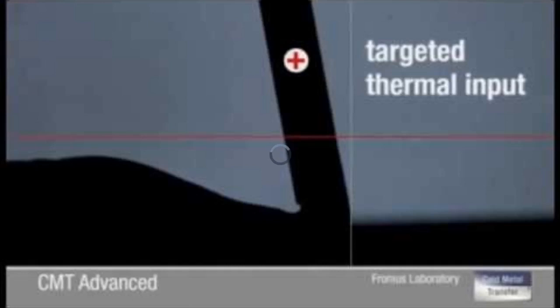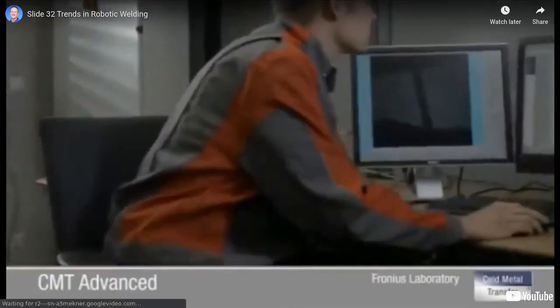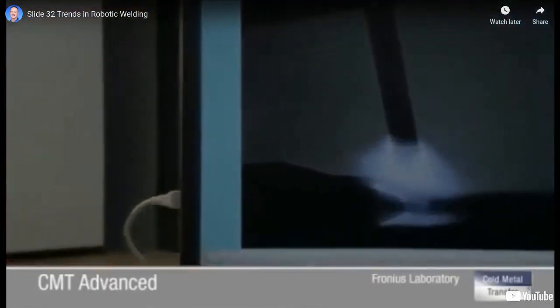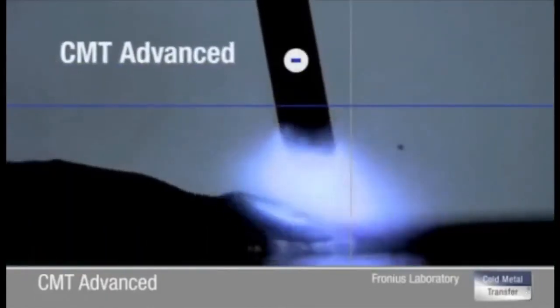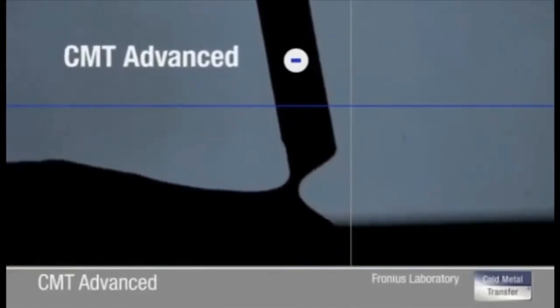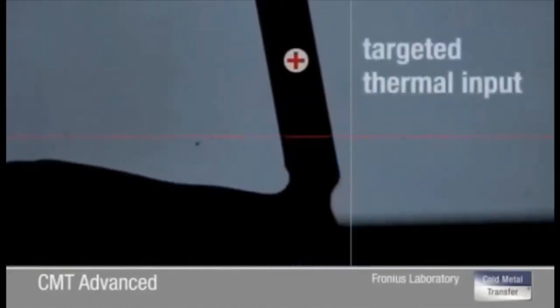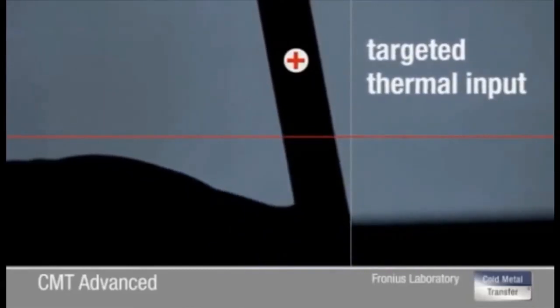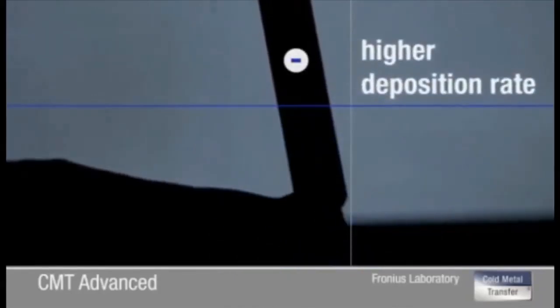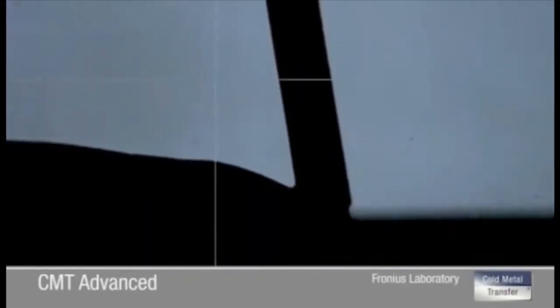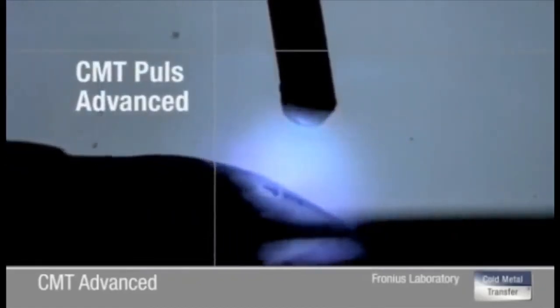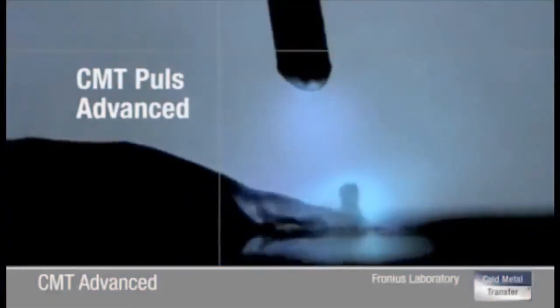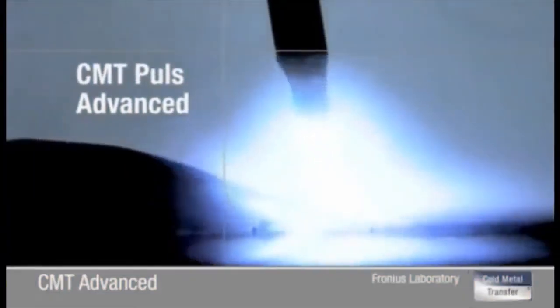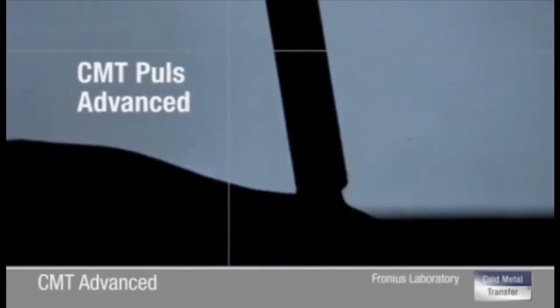You'll see here what that retract looks like from that servo torch. In CMT, the wire motions are fully integrated within the process. In addition, CMT Advanced also reverses the polarity in the short-circuiting phase. The arc remains stable, and the deposition rate is up to 60% higher. Combined with positively charged pulsing cycles, the process makes it possible to join super high-strength steels with complete process reliability. That's CMT Pulse Advanced.